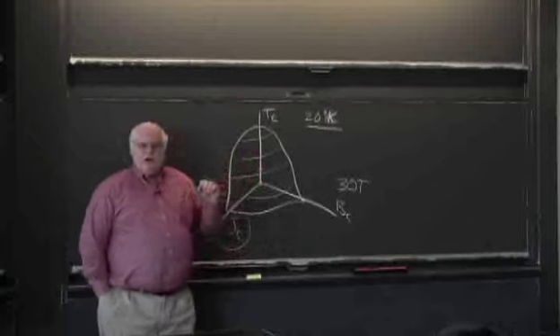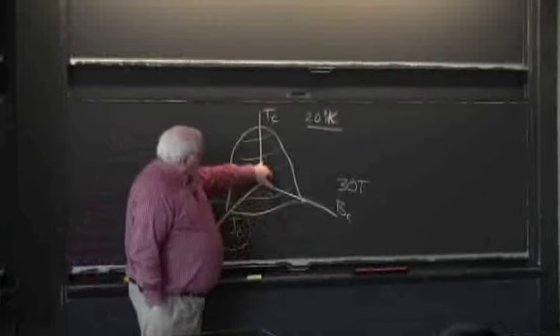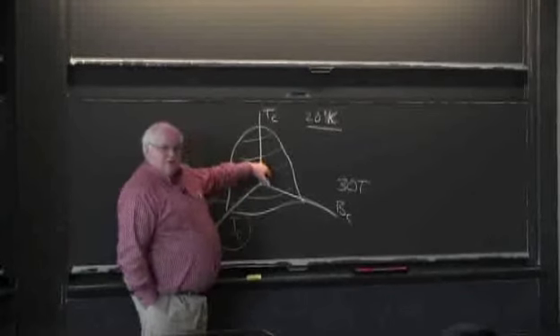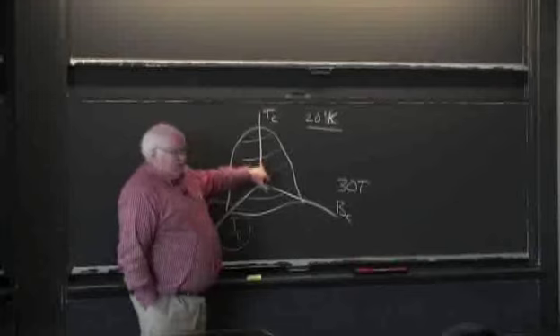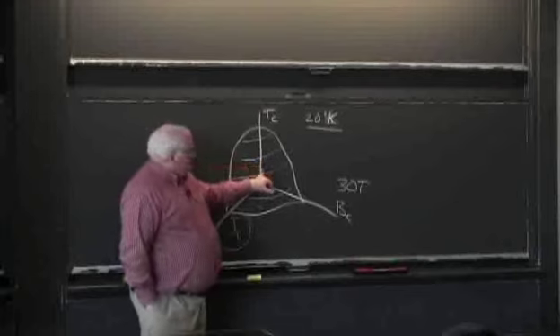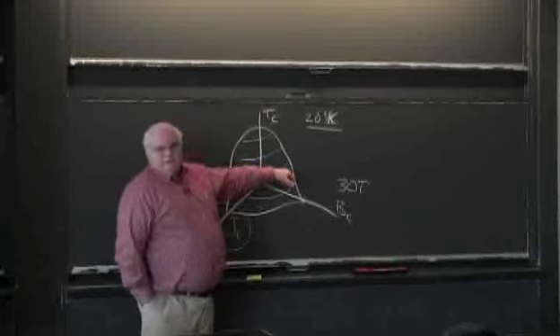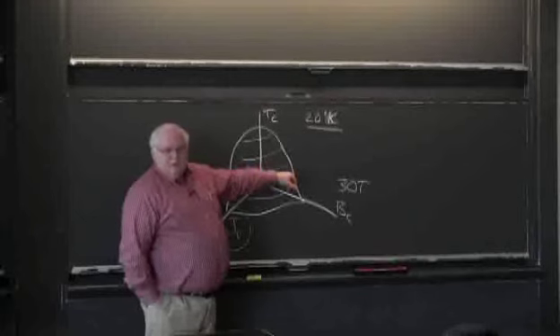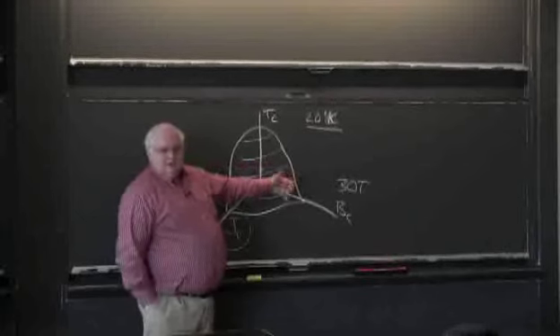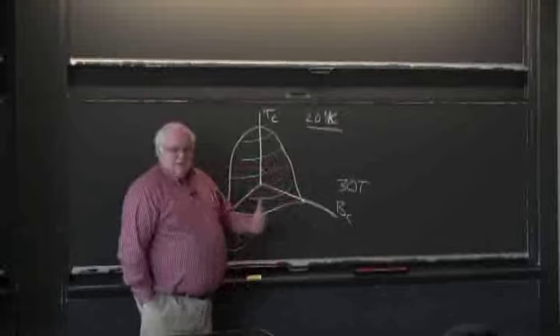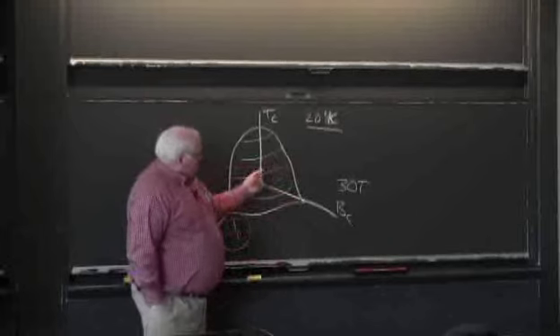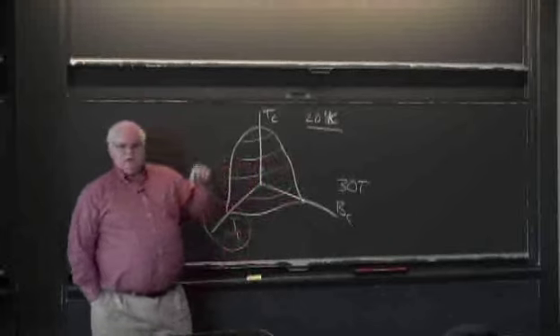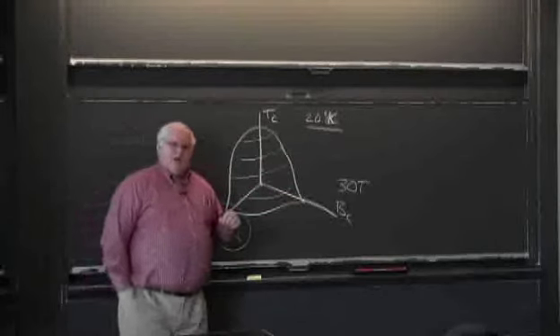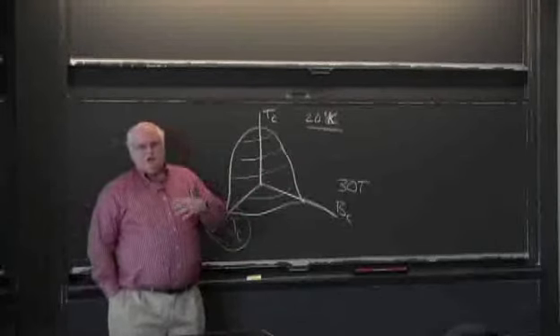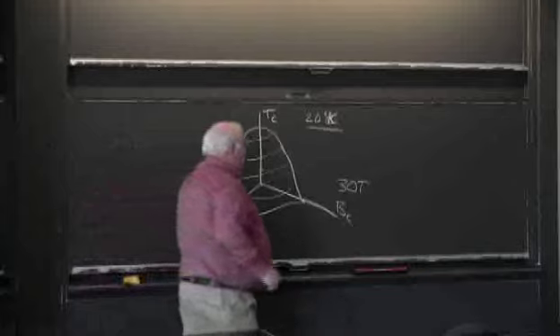John Wolfe had worked on niobium titanium. Niobium titanium had a critical temperature of about 9 degrees. So you were only about double that, and the typical field might be 6 Tesla. Okay, well, that's okay, but it's not great. But then a guy named Mark Benz, who had done his doctoral thesis here in steel making, went to work for General Electric Research, and they came up with niobium three tin.